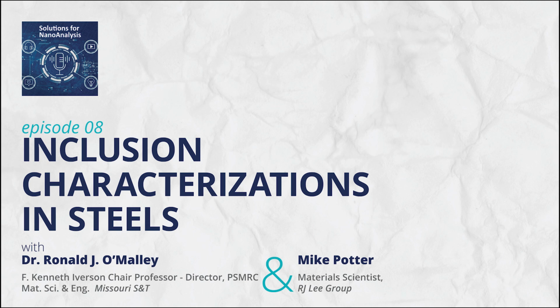I will echo a sentiment. The field emission technology is certainly pushing our ability to analyze into smaller and smaller sizes, making that possible, where previously a lot of that you had to rely even on TEM methods. Things like field emission are starting to bridge that gap between the 1 micron and the nanometer scale to give us a lot more meaningful information in the very early stages of inclusion population growth. So it's actually a really great tool. We've actually worked with Mike on looking at some of those things for new classes of steel, such as high efficiency motor lamination steel, where the inclusion distributions influence the magnetic permeability and core loss of steels used in motors for new electric vehicles, for example.